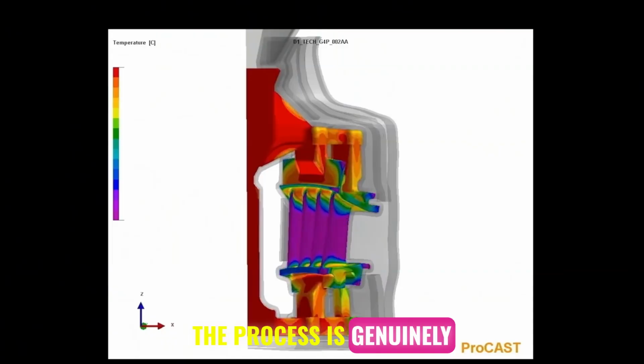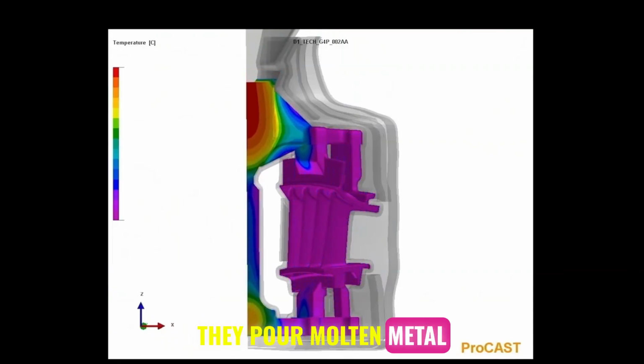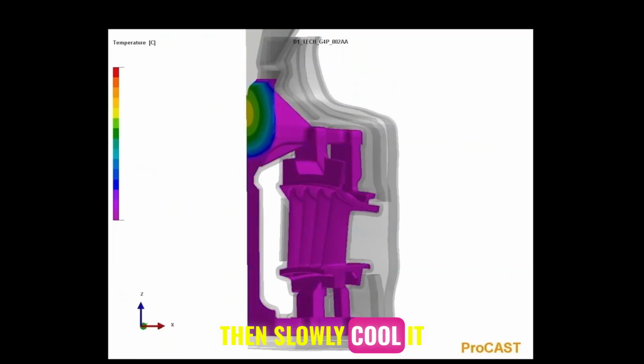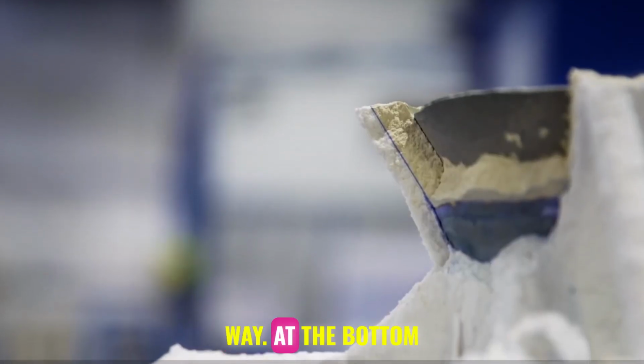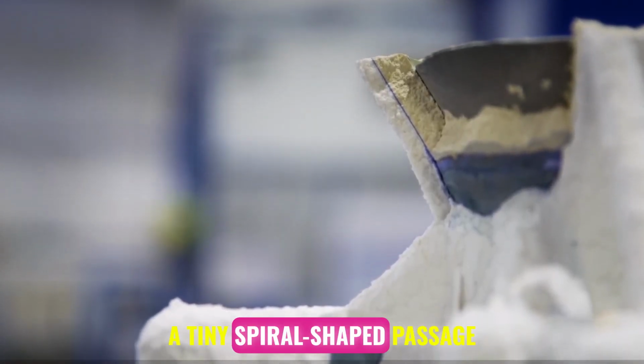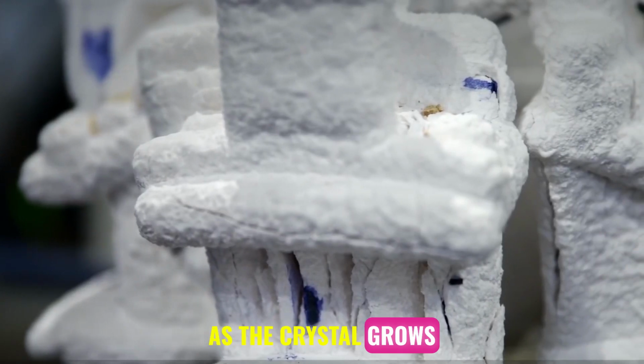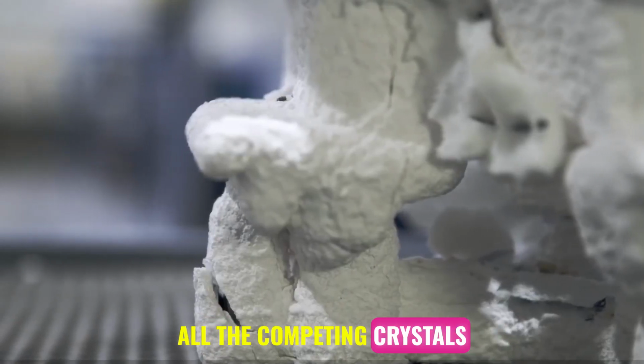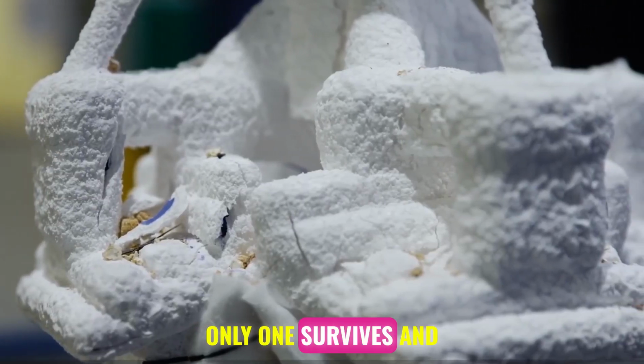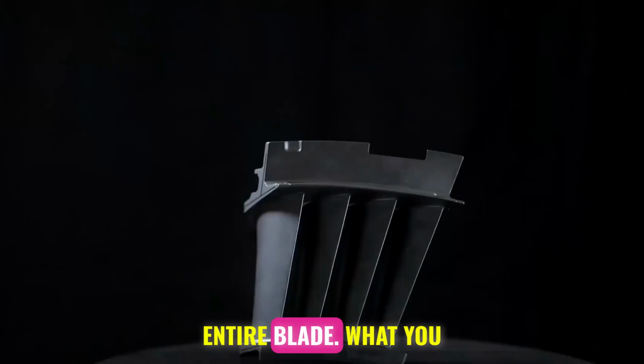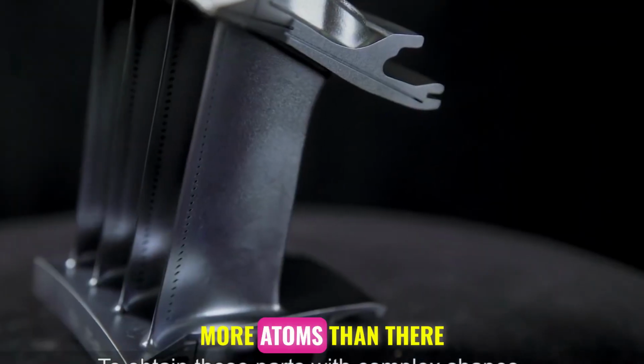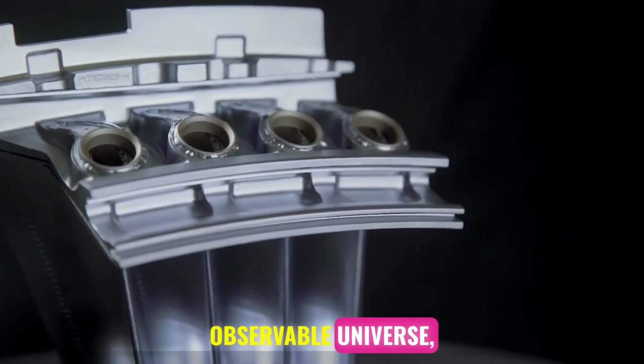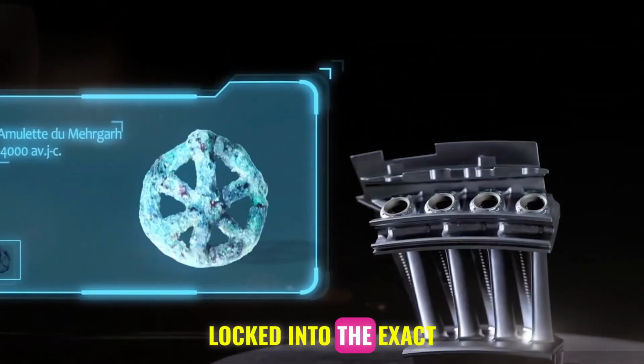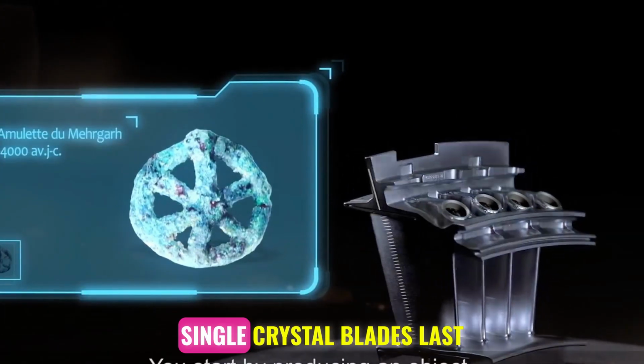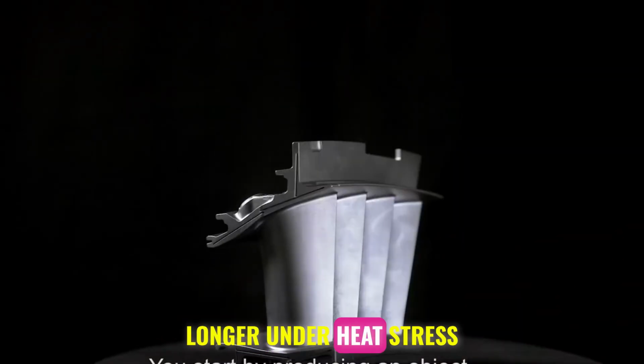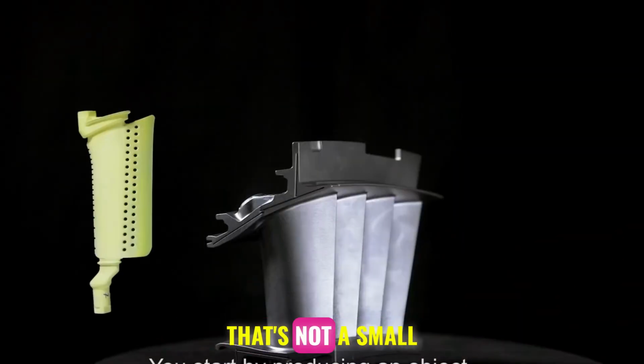The process is genuinely fascinating. They pour molten metal into a ceramic mold, then slowly cool it in a very controlled way. At the bottom of the mold, there's a tiny spiral-shaped passage called a pigtail. As the crystal grows upward through that spiral, all the competing crystals get choked out until only one survives and grows up through the entire blade. What you end up with is a blade that contains more atoms than there are stars in the observable universe, and every single one of those atoms is locked into the exact same crystal pattern. Single crystal blades last up to 9 times longer under heat stress than regular metal blades. That's not a small improvement.